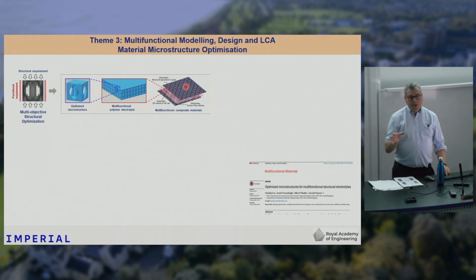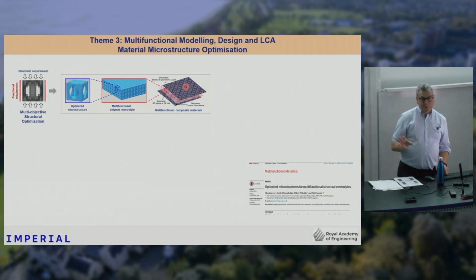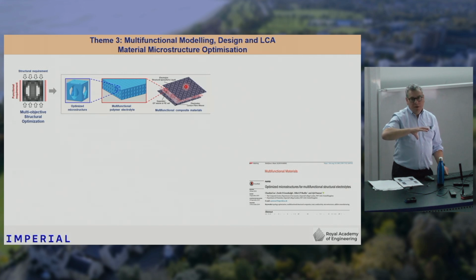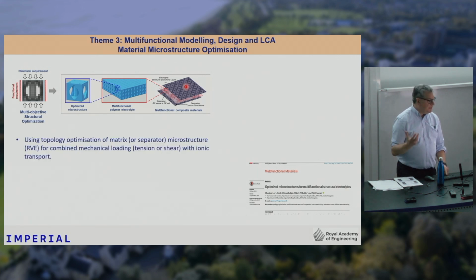So I should stress I'm not a modeler. I'm exclusively experimental in my background, but I'm working very closely with modelers, and they are being guided by my observations to motivate their model development. This work was done with Ajit Panesar at Imperial. We used topology optimization to come up with the optimum motif for our microstructure to give us the balance between mechanical loading in tension or in shear with maximizing ion flow.